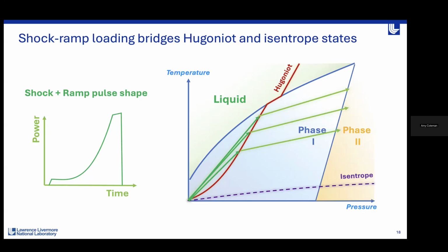So you can see if you wanted to map out this phase boundary, what you could do is tailor your pulse shape so that you're gradually stepping up in shock pressure for one of your shots. You would shock, ramp, and then probe with whatever diagnostic you're using at this state. Then you could do another experiment where you shock to a slightly higher level, ramp, and then probe here.